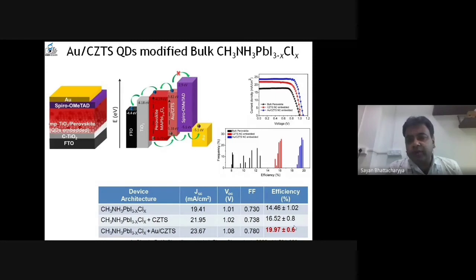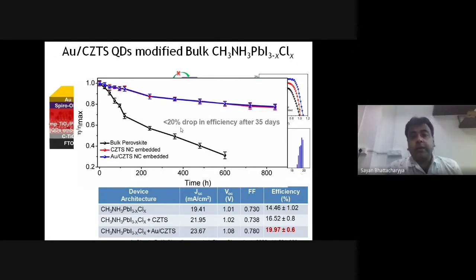Now, in this case, we have reached something like up to 20%. So the world record is 25%, but with a smaller area cell. And here you can see the distribution over the many, many solar cells that we made, the efficiency varies very narrowly. So that means it is more or less consistent and it is reproducible as well. And last but not the least, this efficiency is okay, but stability is also very much important. So what we have seen is that even after 35 days, only less than 20% drop in efficiency has taken place.